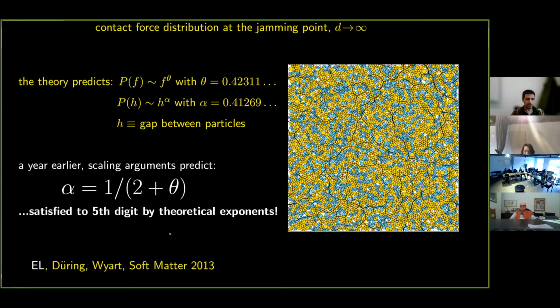And in the same work that I discussed before, by a scaling argument, relying on marginal stability, relying on the fact that any kick to the system would destabilize it and cause avalanches, we predicted that there should be a relation between the exponents theta and alpha. Actually, I'm missing a minus sign here. And it turned out, once the theory came out and these exponents were calculated, that the scaling relation that we proposed was satisfied up to 5th digit. So the theory itself does not predict the scaling relation. You can argue for it by marginal stability arguments. However, the exponents that are extracted agree with it perfectly.